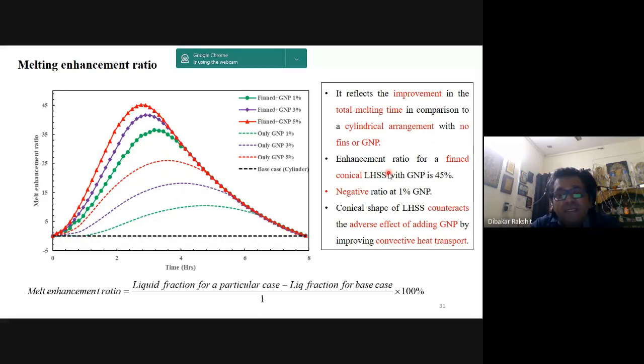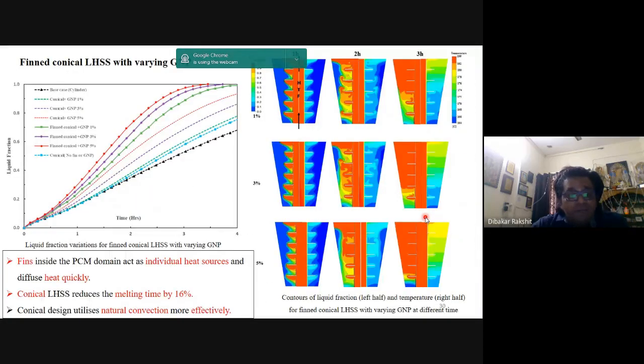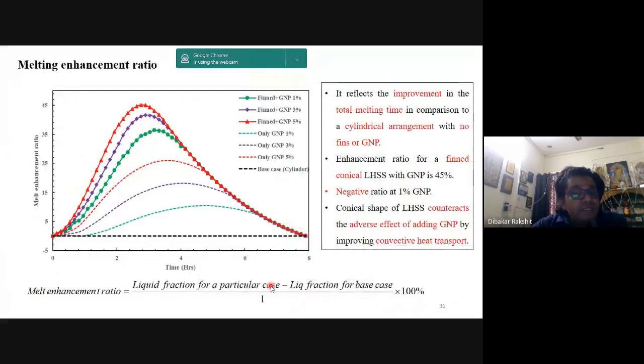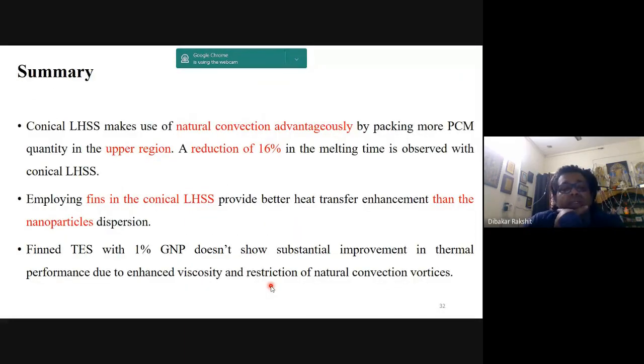And of course, if we utilize only GNP, there is a negative melt enhancement ratio, which is not a very good thing. So we should not use GNP only, with 1% volume. That's what we envisaged. And finally, the conical shape of the latent heat storage system counteracts the adverse effects of adding GNP by improving convective heat transfer, which we have already discussed. The conical design enhances the natural convection effectively in contrast to its cylindrical counterpart. So I think I have discussed it in my previous slide, and that's what is in the summary.